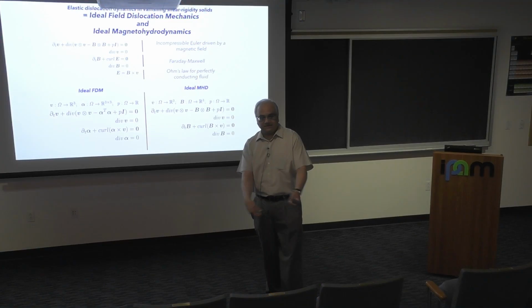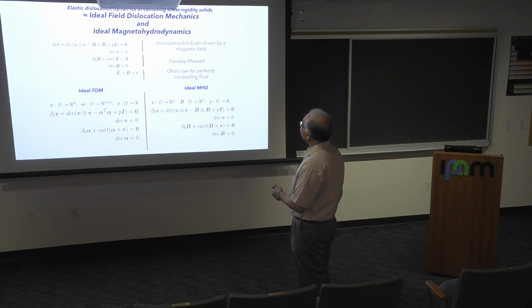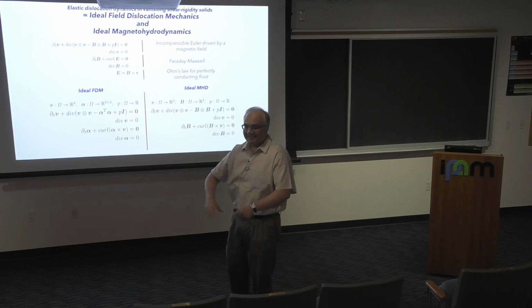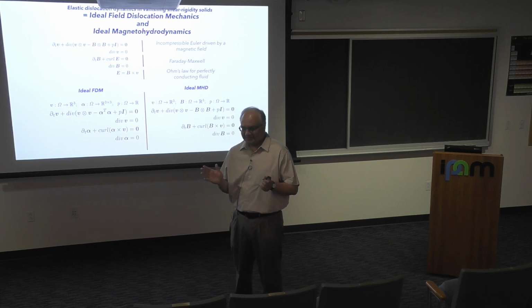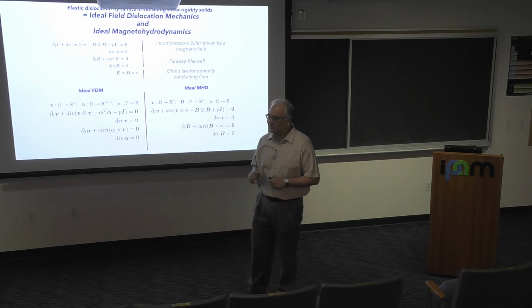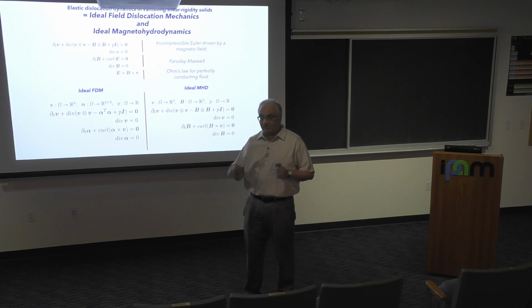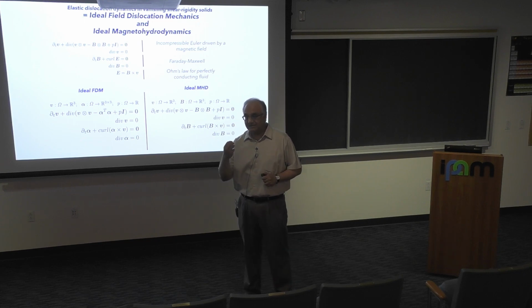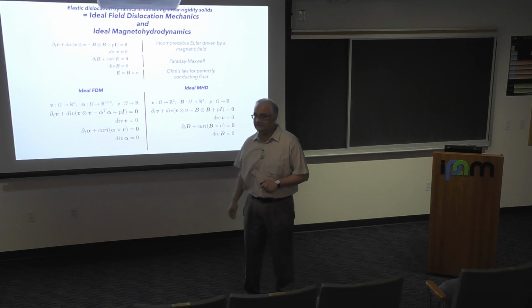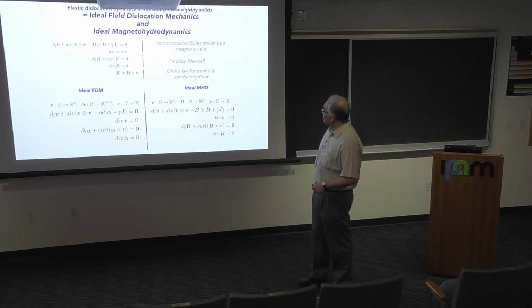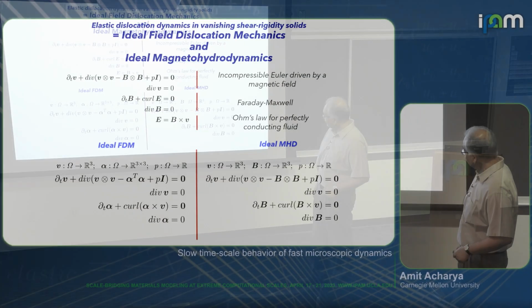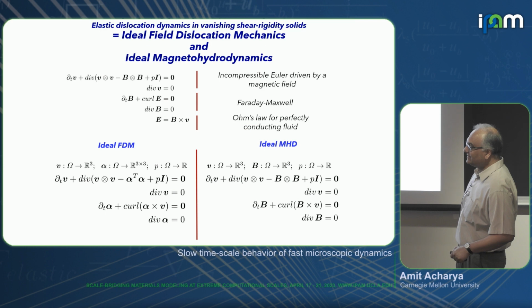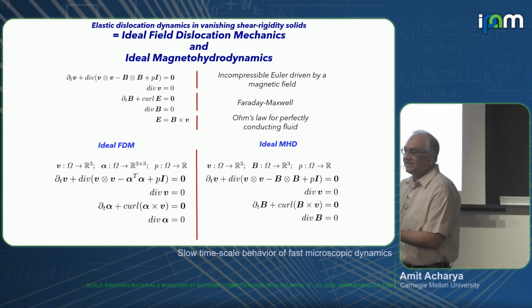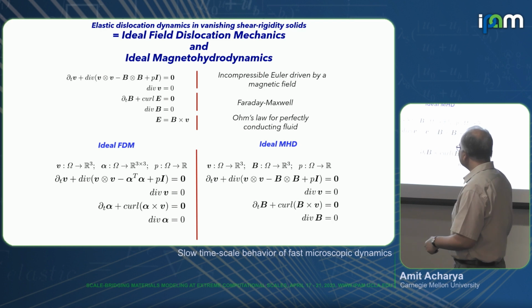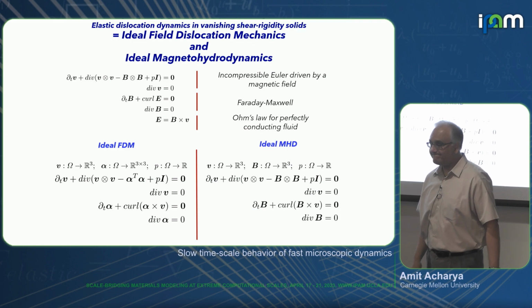If you make the right, okay, so in dislocation dynamics, if you say, no, there are no shear stresses this thing is generating, so this is a solid not generating stress, that's not how it goes. But let's say we drop that, we drop the mobility of the dislocation. So the dislocation only moves with the material. Alpha is a 3×3, B is a vector field, but look, it's exactly so here there's some coupling between the magnetic field and the dislocation density is 3×3, so this has to become a vector. This is how it does, but it's exactly the same thing, okay?